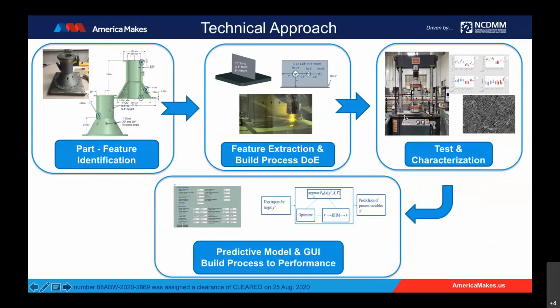This is a pictorial example of the project, where we started off with a part design, a representative part from the aviation and aerospace business, and then we built that. We identified and extracted the features of interest that were critical to that part, as you can see in the second picture in the middle, where you had feature extraction. Then we designed a build process DOE around those features. We built them on the additive machine, sampled and cut sample coupons out of those builds, tested and characterized them, provided those to the data matrix, and built a predictive Bayesian hybrid modeling GUI interface for that.